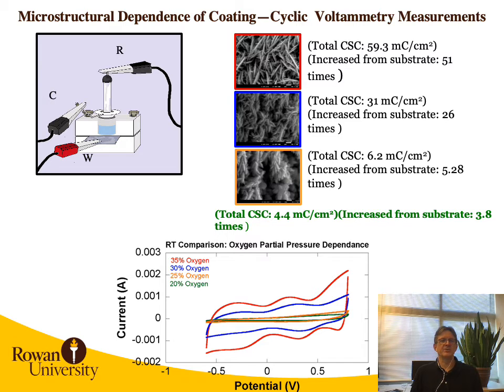If we use the same cell and measure the electrochemical performance of these materials, we see that as the oxygen partial pressure increases, so does the hysteresis enclosed in the 20th cycle here. So this is the 20th cyclic voltammogram. And what we see is that we get 59.3 millicoulombs per square centimeter for the materials that are deposited at 35% oxygen partial pressure. So every one of these materials with the platelets performs better, and as we increase the oxygen partial pressure, we continue to increase the performance, probably due to surface area. If we divide the performance of a flat coating into the performance of these coatings with the interesting microstructure on the surfaces, we see that we get 51 times the substrate area for the effective surface area of these coatings.